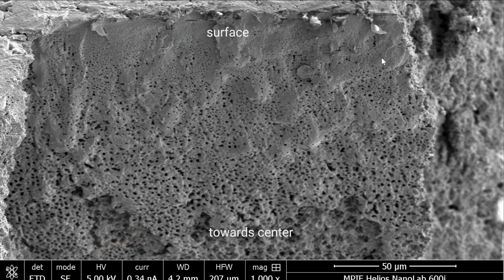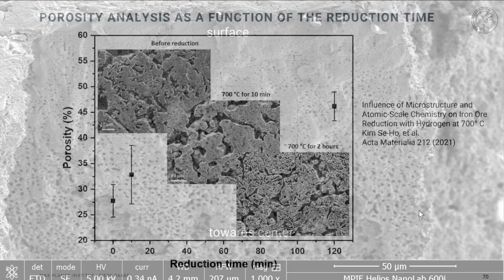This shows a view graph from a single crystalline wüstite from the surface towards the center, and you see a gradient in the porosity. For the reactions close to the surface of the oxide, you see that the material can really leave the free surface. In the center, however, the mass balance leads to a massive porosity formation.